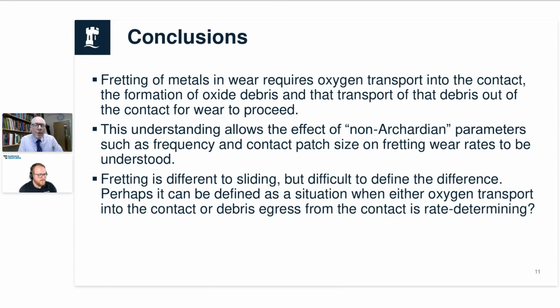No? So we haven't. Well, we have done some work in Nottingham in argon, but there's quite a long history of people doing work in the area of tests in vacuum. What one tends to find is that the wear rates are much smaller, but obviously it's a completely different mechanism. So it comes back to what I introduced at the beginning, I'm talking about things that are happening in air. If you do it in vacuum, you tend to end up with a lot more subsurface damage. So people talk of the tribologically transformed zone, because you haven't got the oxide, which is very protective.